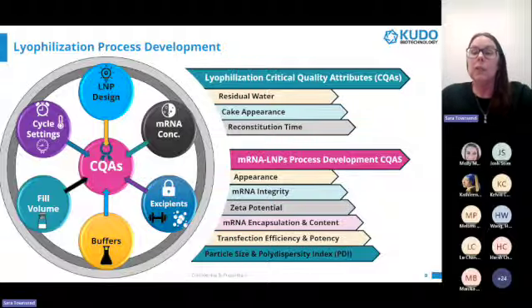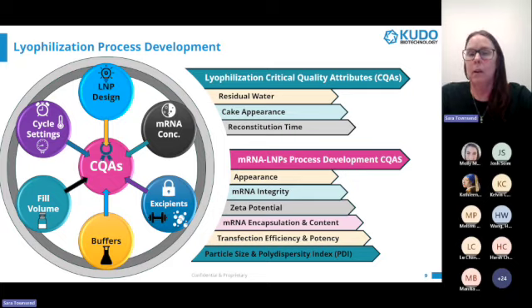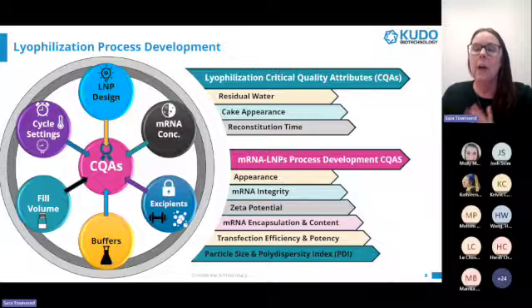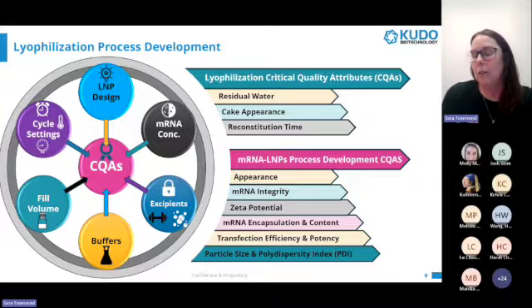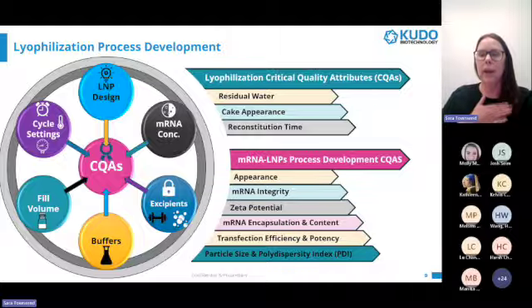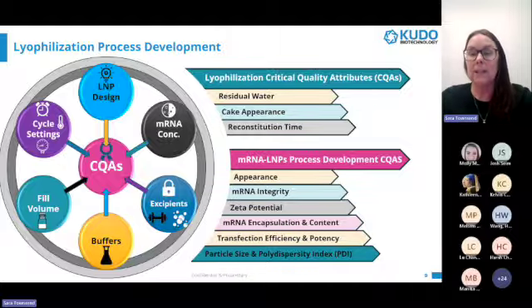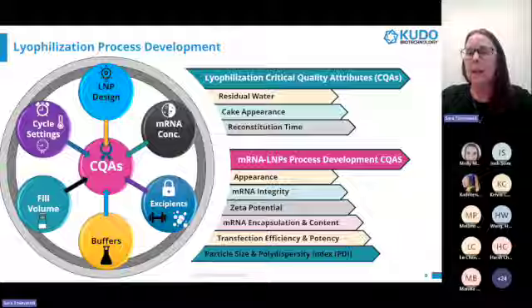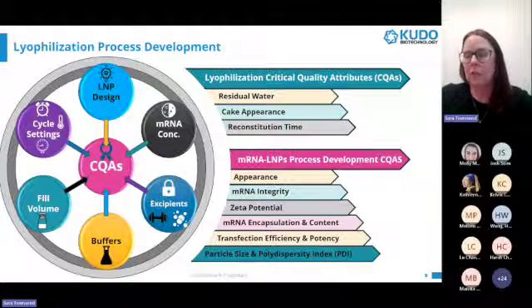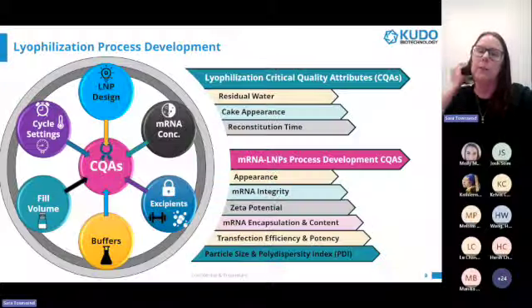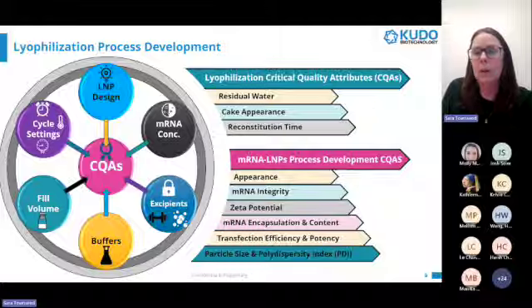Cryoprotectants are typically sugars such as sucrose and maltose and protect the product during freezing and drying. The current hypothesis is that they help protect against particle aggregation by filling the space around the LNPs, and they may stabilize the structure by taking over the hydrogen bonds from the water molecules as the material dries.